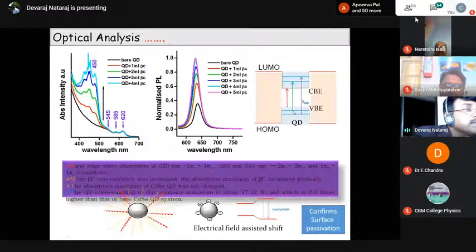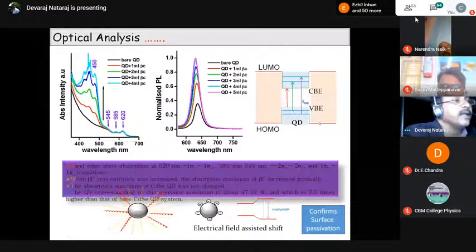You are able to see, as we have seen before, we are having a conduction band offset because the LUMO level of the beta-carotene molecule is a little further away with respect to the conduction band edge state of the cadmium selenide quantum dot. Because of that, there is an increment in the emission yield.